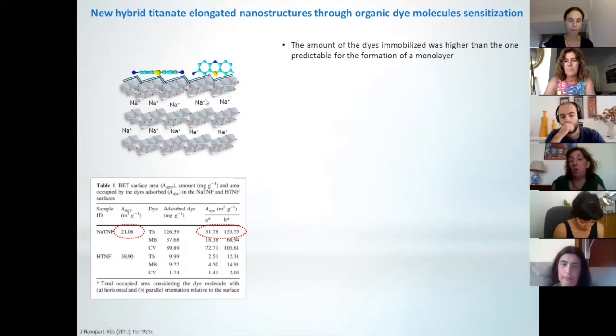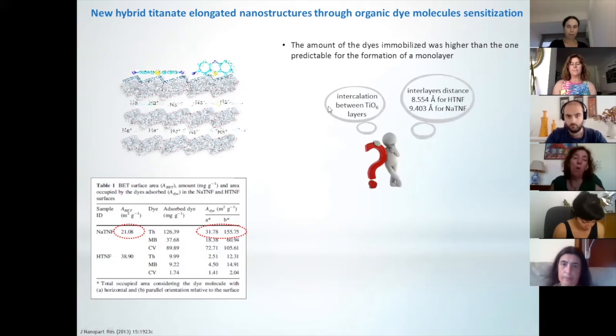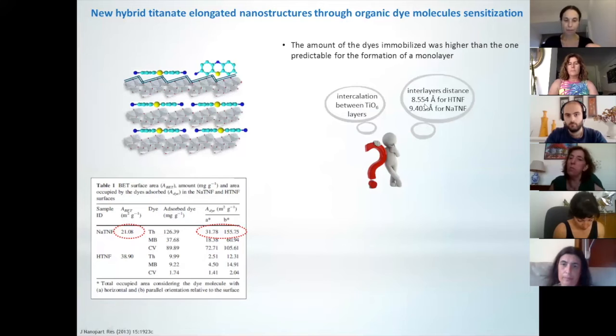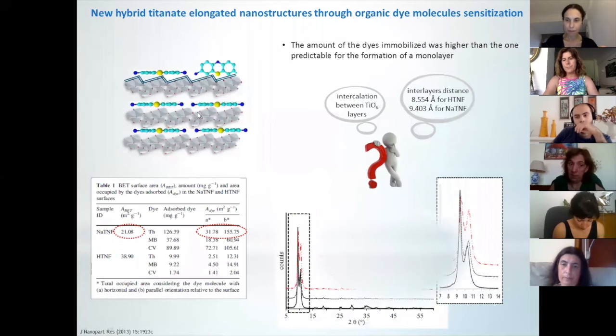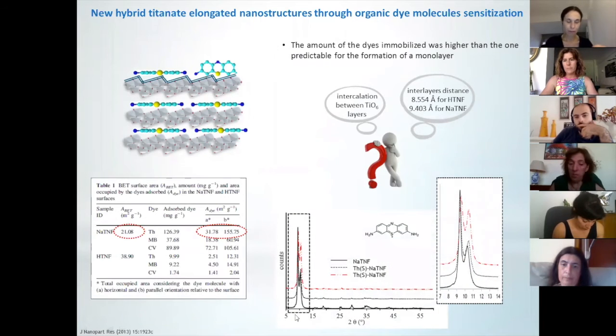So this tells us, oh, I don't have only a monolayer, I have a multi-layer adsorption. Or we try to think about the possibility of having these materials, which are cationic, in the interlayers. Why not? We have the distance that we have, it's more than enough to accommodate these materials. And this situation was confirmed by XRD, for instance. As you can see here, once again, this is the peak that tells us something about the interlayer distance. And when we start to add more and more organic dye, we start to have a shift.